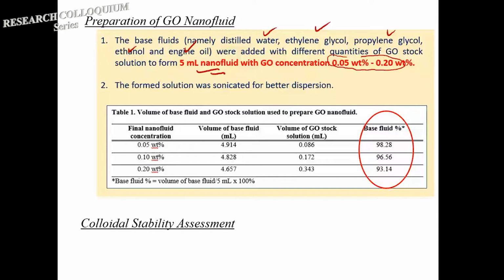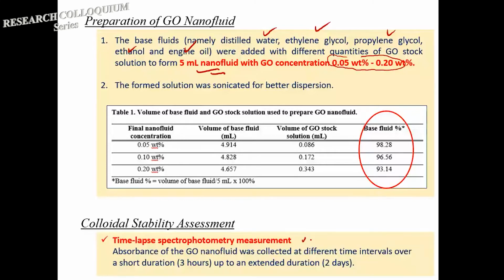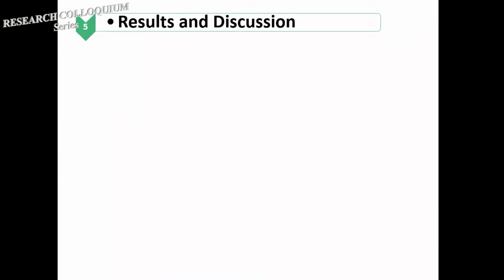And of course, coming to the most important one, we want to assess whether the nanoparticle is stable or not, whether they are going to agglomerate or not. So what we do is time-lapse spectrophotometry measurement. We do the measurement up to 3 hours for a short duration study, and we also continue the study until 2 days to see whether the stability holds for a longer duration. Now, let's go to the result discussion.